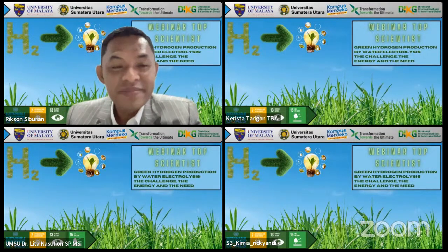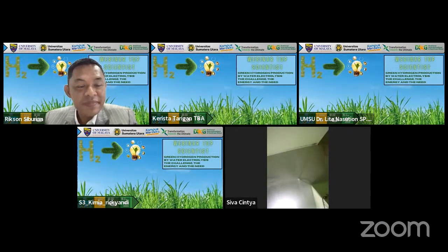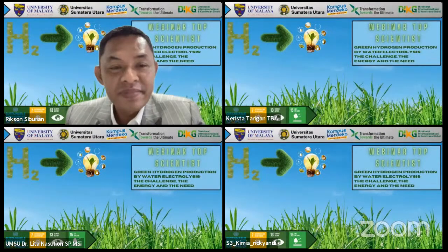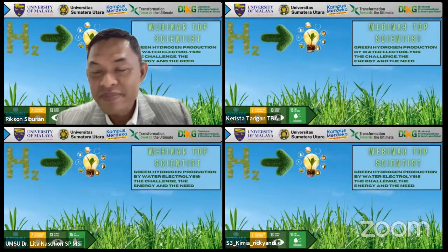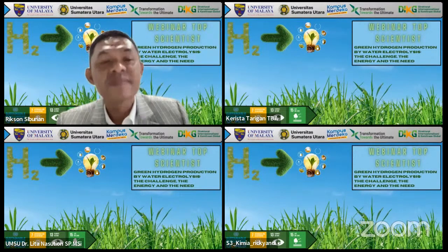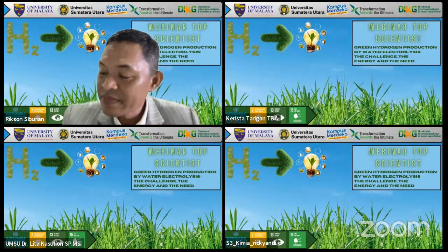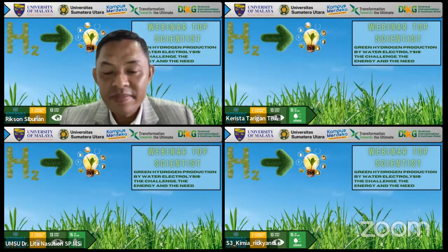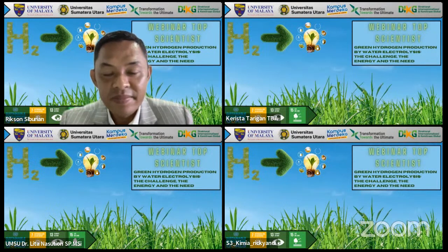Thank you. Welcome. Actually, I already discussed the amount of hydrogen production, because the amount of the electrocatalyst that we use is very, very small. Just to give you some information, we disperse 1 milligram of electrocatalyst in 1 milliliter. Then we drop 5 microliter of this dispersion on the surface of glassy carbon. So this is the amount of electrocatalyst. Of course, we can only detect some bubbles beside the glassy carbon electrode.